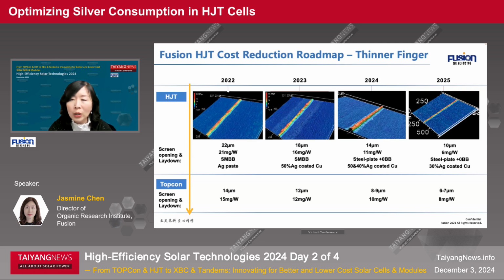But with all the new technology, if the screen opening is decreased to 10, some customers are already realizing it. They use the steel plate, where the opening is only 10 or even narrower, and then with 0BB and 30% silver coated copper, we can get 6 milligrams per watt, which is already lower. The silver consumption is already lower than TOPCon. I hope by next year we can make it into realization.